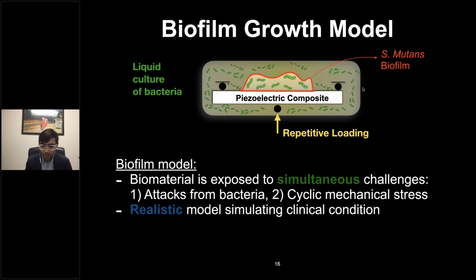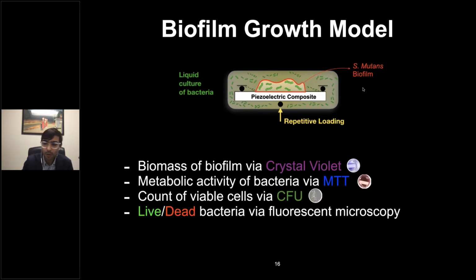The new thing about this model is that for the charges to generate, we needed some type of stimulation, so we needed to apply the mastication load. We submerged the composite into a 3-point bending setup and applied cyclic mechanical load for the duration of the experiment, generating the charges. By doing that, we were expecting first to kill the bacteria, and as we'll see later, to generate minerals. This model replicates a more realistic environment, because that's exactly what happens in our mouth - we're chewing these materials for 200,000 to 300,000 cycles a year.